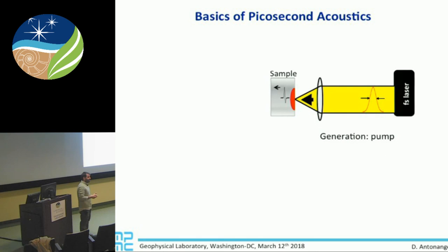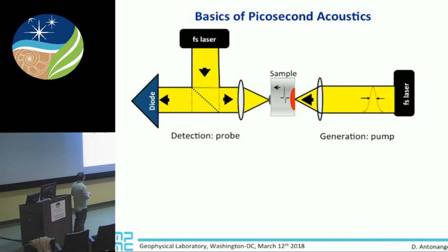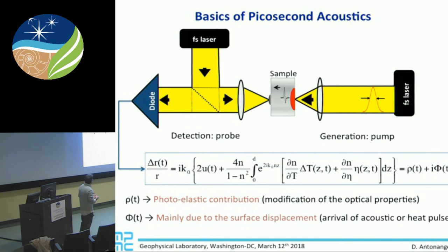Picosecond acoustics is a complementary laboratory technique, a pump-probe optical method developed over the last 20 years, mostly to look at mechanical and thermal properties of thin films. What we did was to develop a setup to use the same technique in the diamond anvil cell. A femtosecond pulse is focused either on a metallic sample or on a transducer. When it's absorbed, it generates a small and sudden temperature increase. A few degrees are enough to generate a thermal stress. This thermal stress relaxes, launching a longitudinal strain field, which is an acoustic echo that propagates across the sample